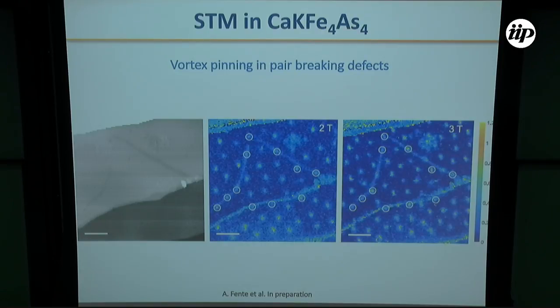And when we look at the position of the vortices, we find that some vortices are placed on top of these defects. And the vortices which are there don't change their position when we change the magnetic field. Whereas the vortices which are between these defects change their position when we increase the magnetic field. This indicates that the vortices are strongly pinned to these pair breaking defects. And probably these pair breaking defects are the most important contribution to the pinning in these samples.